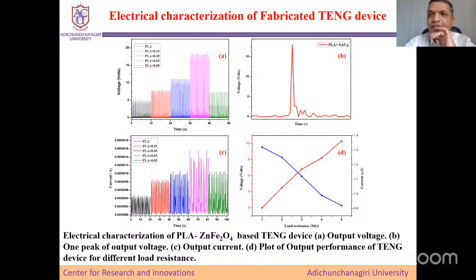The first graph indicates voltage versus time. You see here, it is just PLA, and then PLA with 0.25, 0.45, 0.65, and 0.85 percent. Sorry, it is not grams, it is percentage of ZnFe2O4. As it increases up to 0.65, it gives a very high voltage of between 15 and 20 volts. But the moment you increase to 0.85 percent, the texture is damaged, thereby decreasing the voltage.